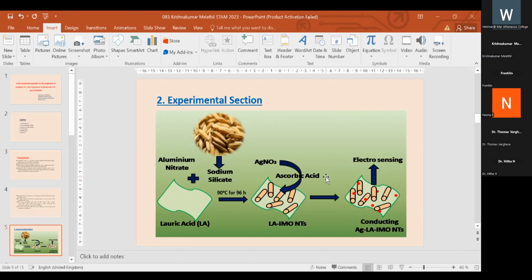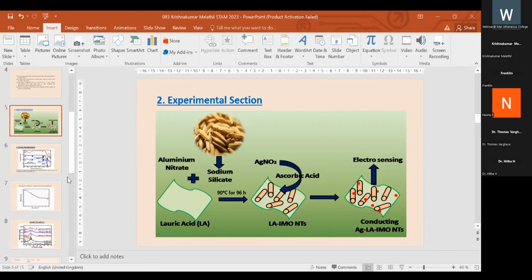After adding the sodium silicate, we slowly set the pH to circumneutral, that means 7, using low molar sodium hydroxide. After that, at 90 degrees Celsius, we do hydrothermal treatment in an autoclave for 4 days. After that, we purify this material and load silver onto the imogolite, using AgNO3 as the silver source and ascorbic acid as the reducing agent. We coated this material on a carbon paste electrode and used it for electrosensing studies of nitrophenol.